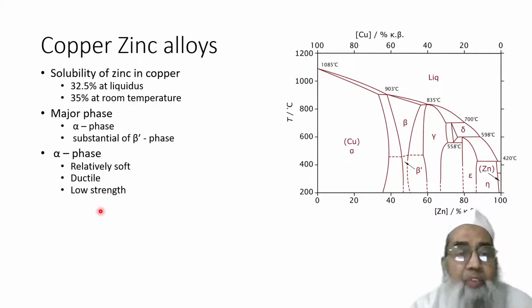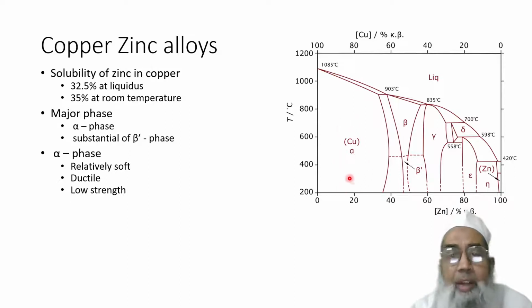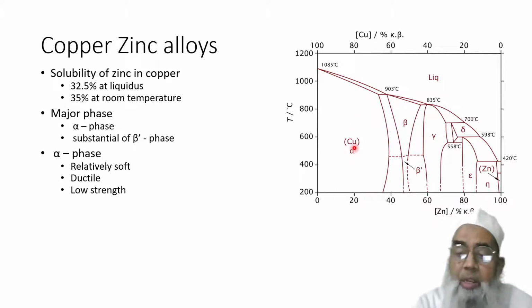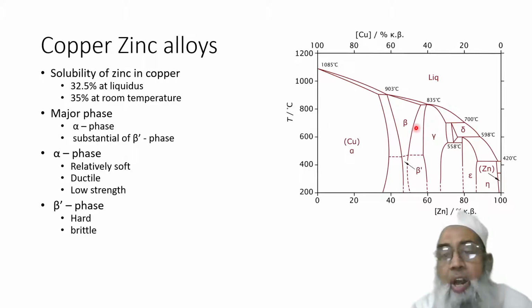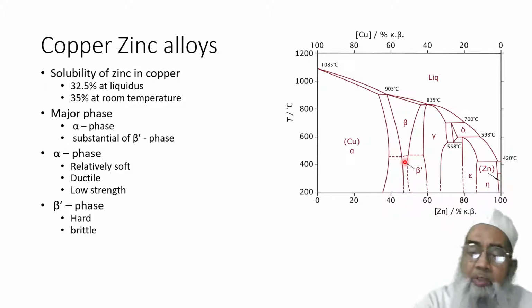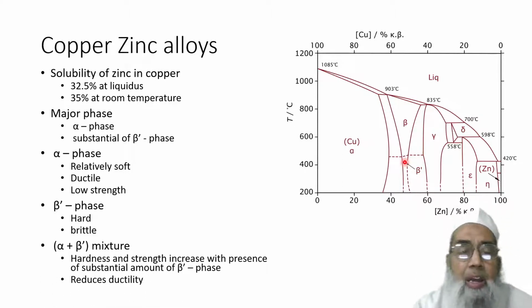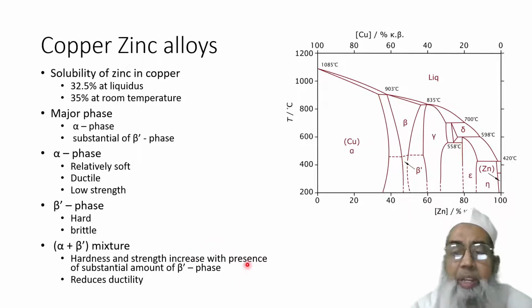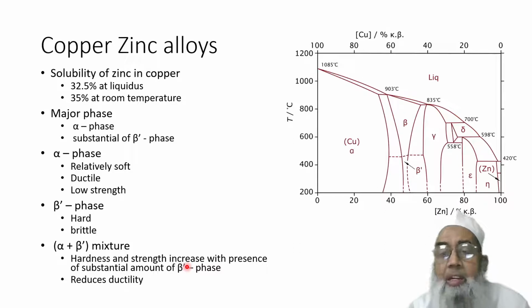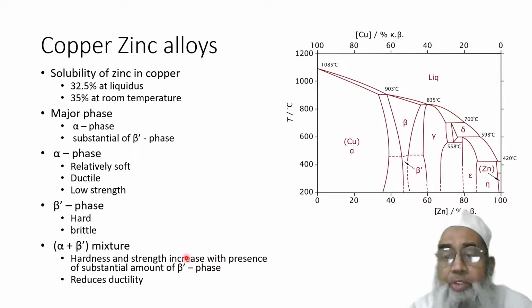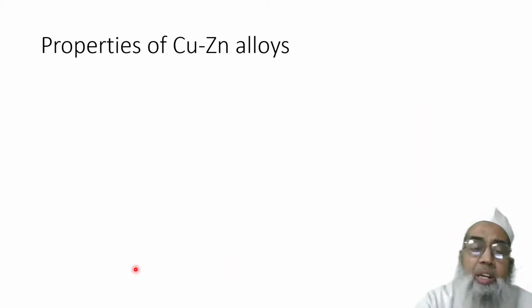See, now the alpha phase is relatively soft and ductile, having low strength, while the beta phase is hard and brittle. Therefore, with the amount of alpha plus beta phase, the hardness will be given. The hardness and strength increase with the presence of beta phase, but at the cost of ductility, of course. Therefore, for a particular application we have to optimize how much hardness we need and how much ductility will be reduced.